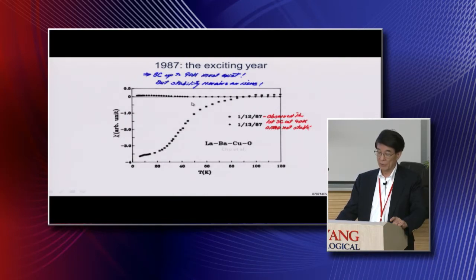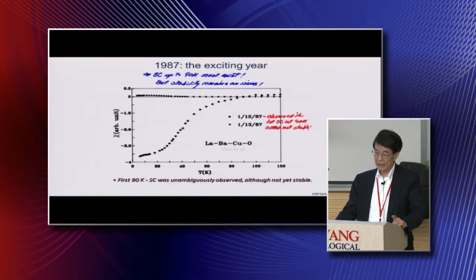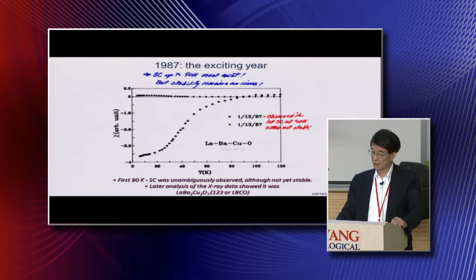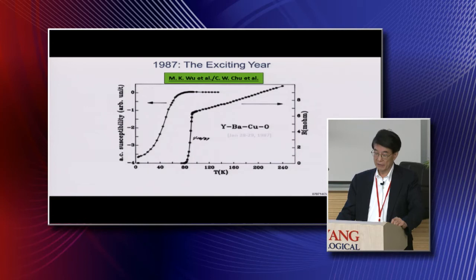So later on, we did the magnetic measurements, on January 12, 1987. And indeed, we saw the Meissner effect starting at around 100 degrees Kelvin. So that was sure that superconductivity above 77 degrees would take place. And the problem is how to stabilize it. Later on, when we go back and look at the structure of this compound, this is a mixed phase compound, and it turns out the lanthanum barium copper oxide 1,2,3 phase is there, but at the time we did not recognize it. And then on January the 29th, 1987, my student M.K. Wu, with whom we collaborate, and Chu, did stabilize the YBCO with a TC above 77 degrees.